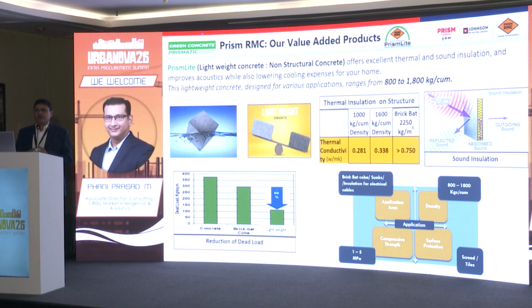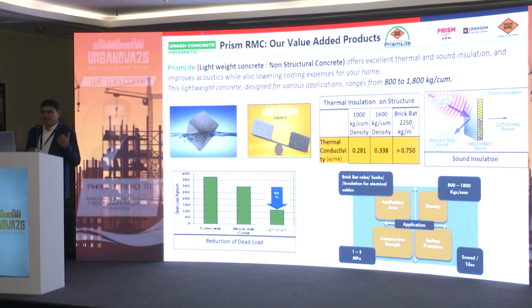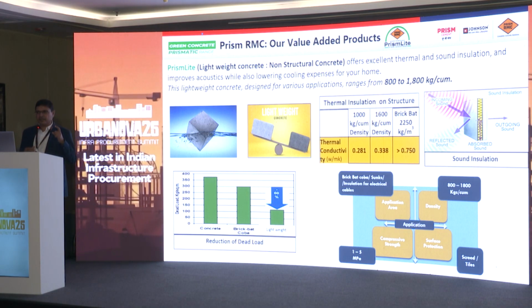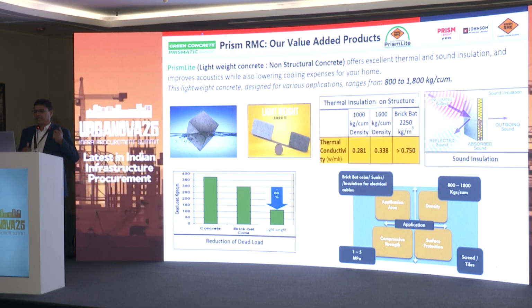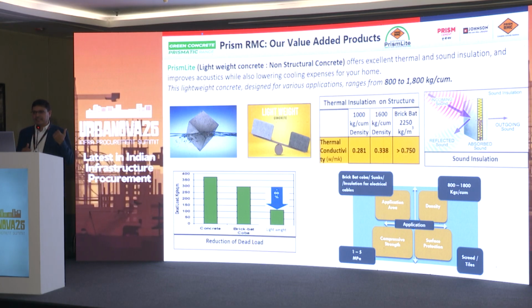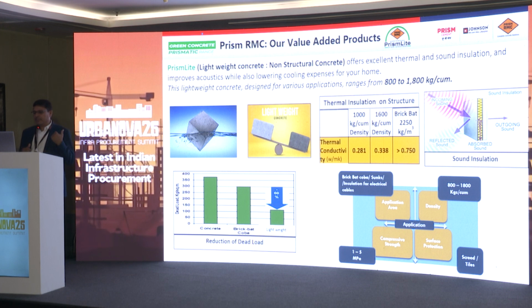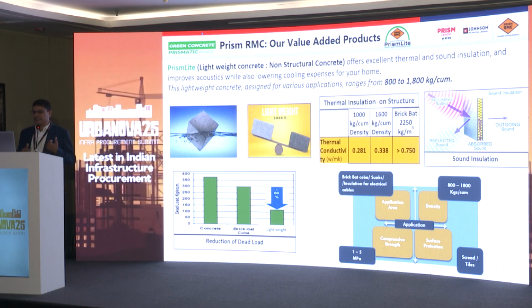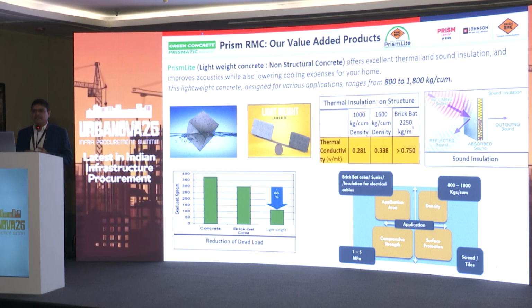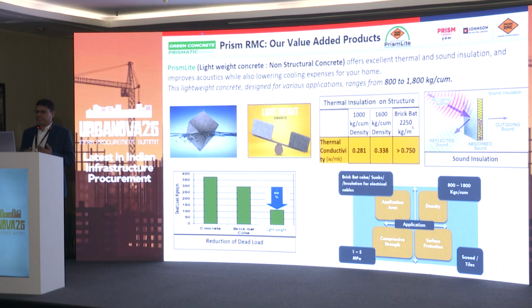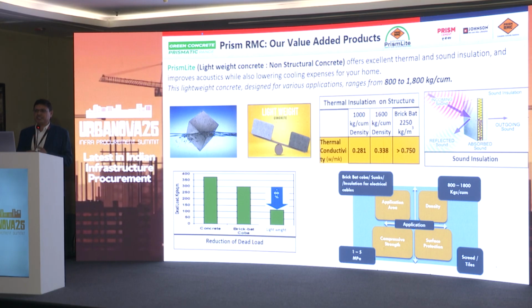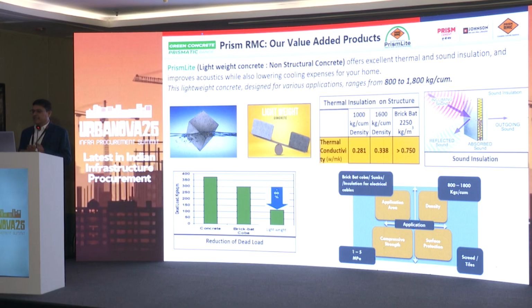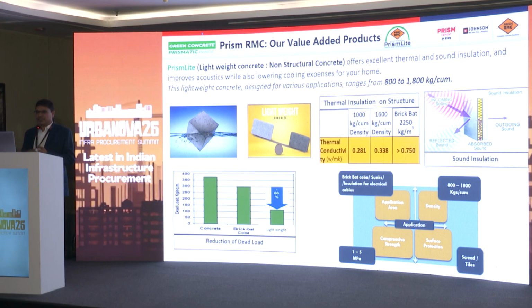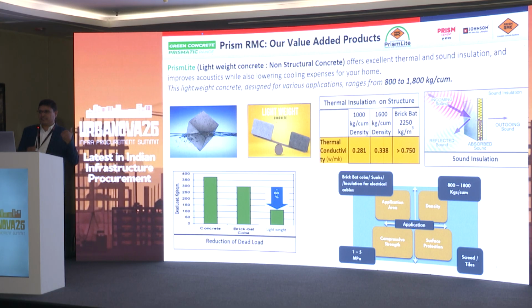It is very good for the reduction of the dead load. In the graph you can see, suppose you consider a slab of 150 mm with 2500 kg per meter cube density, the dead load comes around 375 kg per meter square. If you consider a density of 1000, then it is just 150 kg per square meter. So 60% dead load we can reduce by using this concrete. Second, it is very good for sound insulation. The challenge is only the strength.